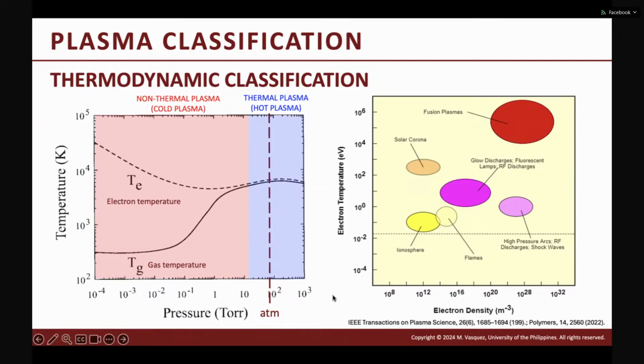Now, another classification of plasma is in terms of its temperature. This graph here shows that at low pressure, you have the separation of electron temperature and gas temperature. At low pressures, usually the electron temperature is relatively high compared to neutral gas temperature. As you start increasing your pressure, this difference becomes smaller. And once it reaches near atmospheric conditions, then TE and TG are almost the same. And that's the beauty of using plasma, because you have this broad energy range that you can use to modify different surfaces or materials.